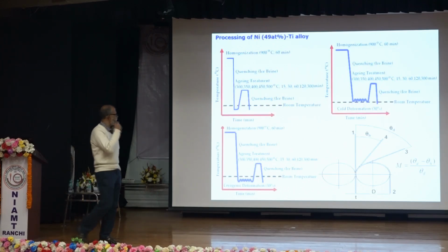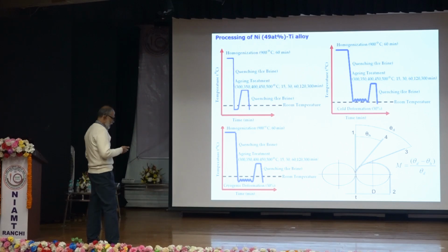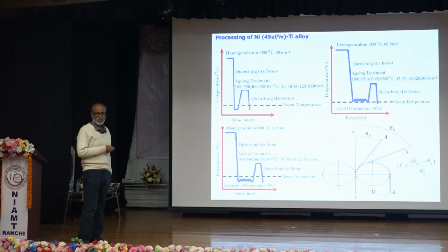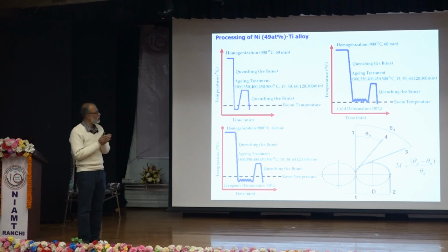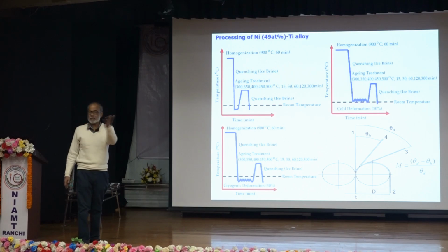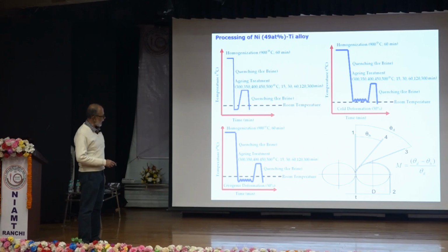So we thought of certain experiments, and the first thing that occurs in our mind is aging, because we have seen there are intermetallic phases associated with the 50 titanium nickel composition. So if we do certain aging, we expected some precipitation will occur. We deformed it before aging because deformation creates a strain field which accelerates aging and results in uniform distribution of fine precipitates. So we deformed it in ice water, and we also deformed it at very low temperature.